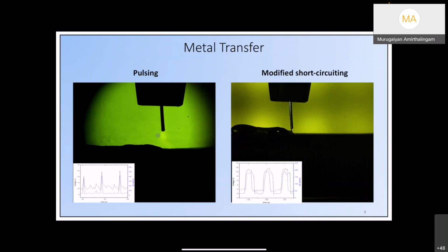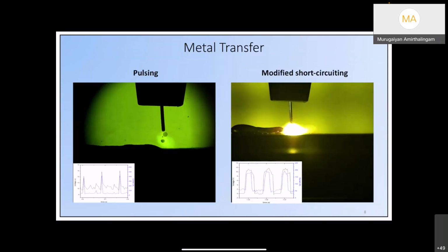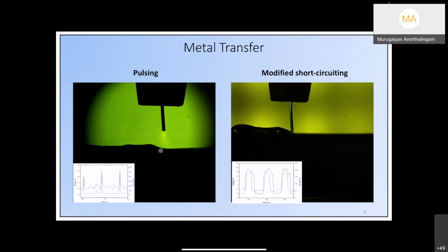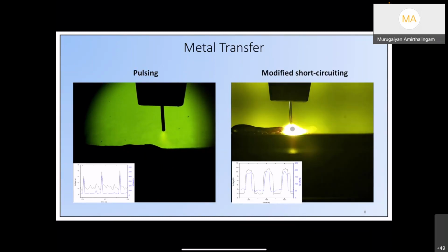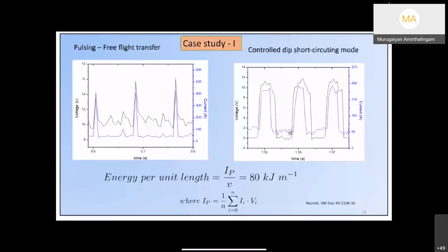You see over here, the droplet is detached in a free flight manner to the molten pool, or we can also do a short circuiting transfer. In short circuiting transfer, the droplet is attached and transferred to the molten pool by a dipping event, by dipping the molten wire and the droplet into the pool. And how do we control that? The current voltage waveform we use is going to influence the droplet temperature and the molten pool we create.